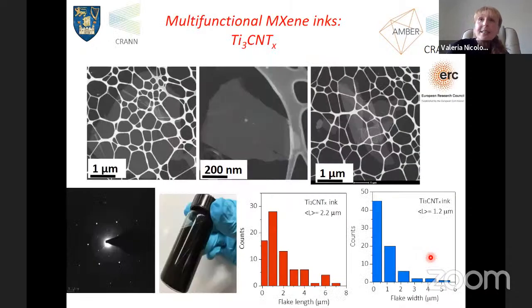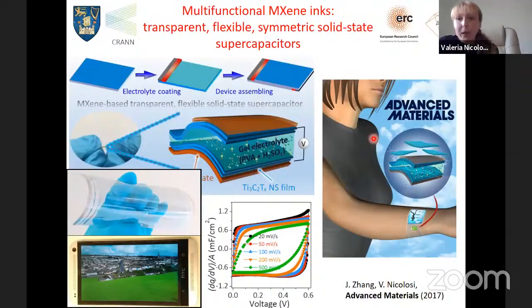It is extremely concentrated, and this is what we use for a lot of our applications. These are the types of layers that we get, nice and thin, much thinner than what you get with van der Waals structures, and much wider as well, reaching several microns in size. Normally, liquid phase exfoliated van der Waals materials exfoliate into much smaller fragments. So what we have been able to do is use these inks for a lot of different types of applications in the energy storage space, but not only.